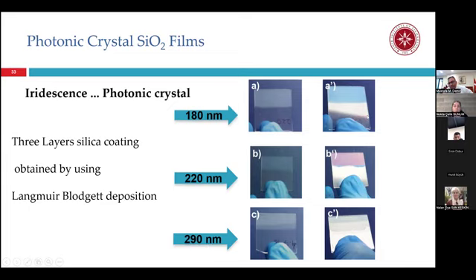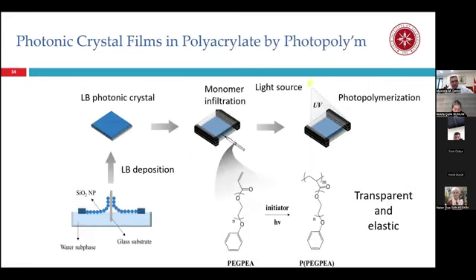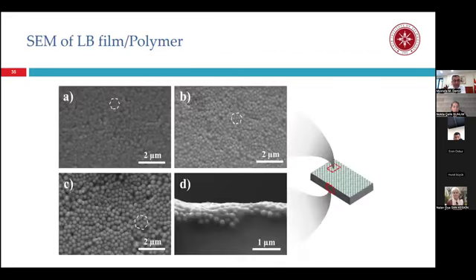So you see different colors, okay? And they are iridescent colors, and we sandwich this photonic crystal between two glass slides. Since they don't have any scratch resistance, we had to be quite gentle, and using a syringe, we put some monomer inside the space of the sandwich. It was poly(ethylene glycol) phenyl ether acrylate. Then we apply photopolymerization. Okay. Then at the end, after polymerization is finished, we obtain a transparent and elastic material.